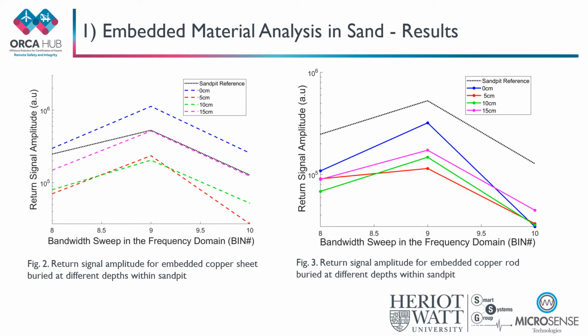Figure 3 highlights a similar trend for the copper rod buried at different depths within the sandpit. The copper rod, however, has a much smaller surface area, therefore returns a much lower return signal amplitude when compared to the copper sheet at each embedded depth. These results enable for detection of depth of embedded material.